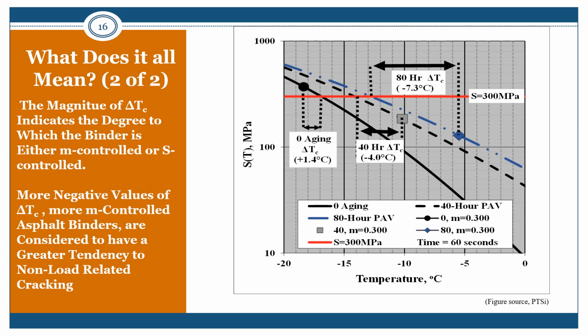In this presentation, delta TC values are presented as degrees Celsius. It is important to understand that the delta TC value represents a difference in temperature, Celsius degrees, as opposed to a specific temperature. Additionally, the negative value does not represent a negative temperature, but that the parameter is M critical, creep rate controlled. Again, the magnitude of delta TC value indicates the degree to which the binder is M controlled or S controlled. The industry has pretty much accepted the degrees Celsius nomenclature, so we'll use this throughout the presentation.